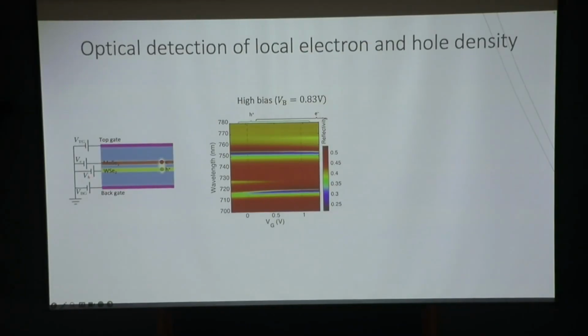Now, if we have two layers together and we do optical spectroscopy, you see the two layers are two different semiconductors. They have different band structures, and then they have different exciton resonances. As a result, we can read them out separately. This peak is the WSe2 exciton resonance, and this peak is the MoSe2 exciton resonance. And when we change gate voltage, we can see here, hole is doped in the WSe2.